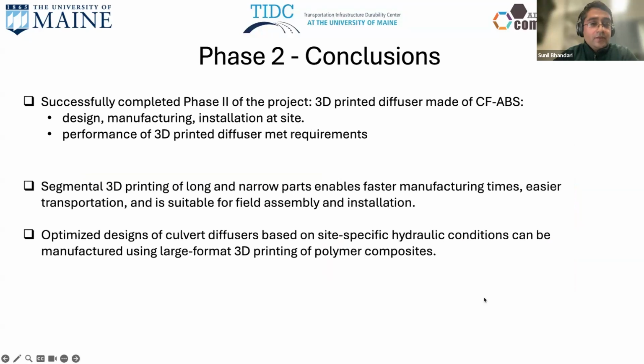So the conclusions for phase 2 of the project: we successfully completed phase 2. We designed, manufactured, and installed the diffuser at site. We saw that the performance of the 3D printed diffuser met the requirements. Segmental 3D printing was effective, and it allowed faster manufacturing time, easier transportation, and the produced segments are suitable for field assembly and installation. And we also found that optimized designs of culvert diffusers based on site-specific hydraulic conditions can be manufactured using large format 3D printing of polymer composites.